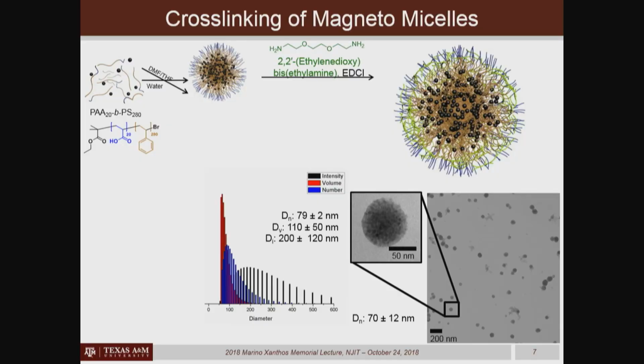And when this assembly is done in the presence of inorganic iron oxide nanoparticles, those inorganic iron oxide nanoparticles get trapped within that polymer micelle. And so we do this by starting with organic solvents and then transitioning over to water, and ultimately these micelles are suspended within an aqueous solution. We then add, say, diamines and a carbodiimide activating agent to form amide bonds, where we consume a fraction of these acrylic acid groups, and that then stabilizes this structure. So again, this was the overall design.